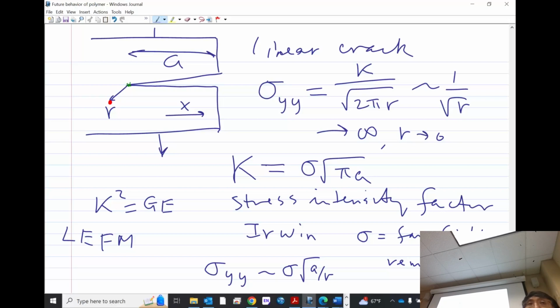So this is a mathematical result. How much intuition can you derive from it? Well, you derive it by soaking in that this is the behavior of a purely linear elastic material as it approaches the crack tip. Where the crack tip is a line crack, so it's very sharp, infinitely sharp, mathematically thin, infinitely thin. So, what's the trouble? Everything is fine except when you consider this goes to R equals 0.